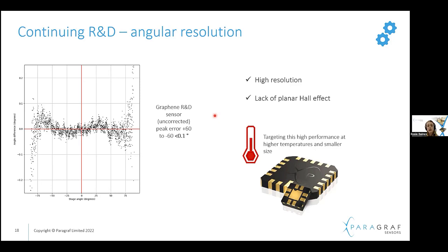So it would be good to target this kind of high performance at higher and higher temperatures and at smaller and smaller size. So this is very much something that's in progress. Looking at, for example, this kind of size reduction, this is a standard package, and then moving down to a much smaller one where the active area goes from the millimeter scale to the tens of micron scale. So that opens up a range of improvements there.